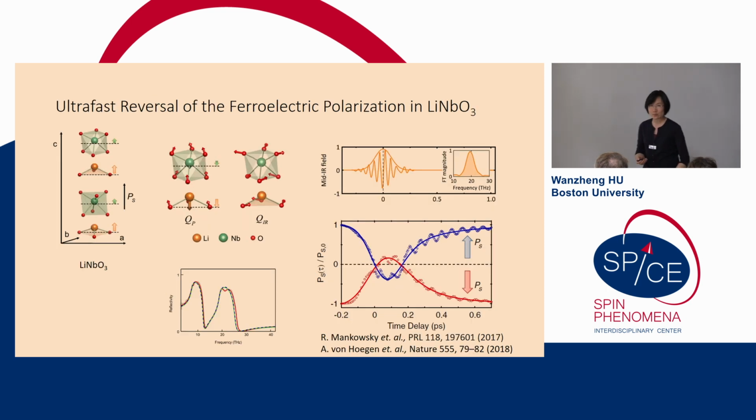This is a very interesting prediction, and there is a pioneering experimental work done by Roman Mankowsky, where he chose lithium niobate, a very classic nonlinear crystal. Lithium niobate is ferroelectric at room temperature. We can view this ferroelectricity as coming from cations moving off center of the octahedra, and here this cation also moves out of the oxygen plane. So lithium and niobium both contribute polarization along the same c-axis direction.